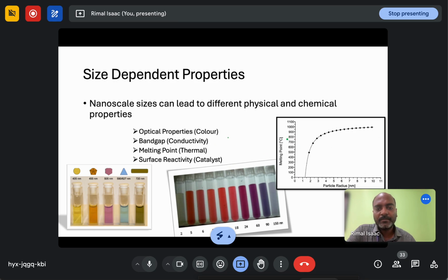So, when you look into the melting point, you can see the bulk material, or if the particle radius is around 10 nanometers, for gold the melting point is around 1000 degrees Celsius. But if the size is reduced to around 2 nanometers, the melting point also reduces drastically to around 500 degrees Celsius. The material is the same, it is gold, but the reduction in the size happens, that is we are reducing the size from 10 nanometers to 2 nanometers, and the melting point of the material reduces by half. So, theoretically what we study is, whatever the material it may be, the melting point is the same, it never changes, but when we convert the material into a nanoscale, the melting point depends on the size of the particles.